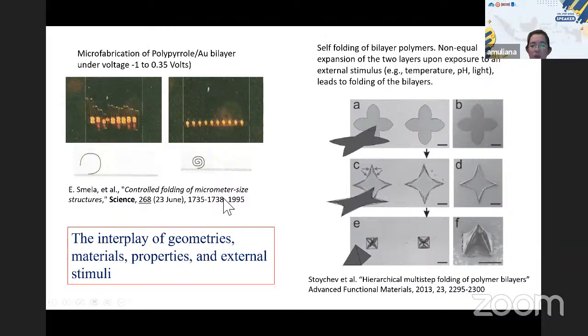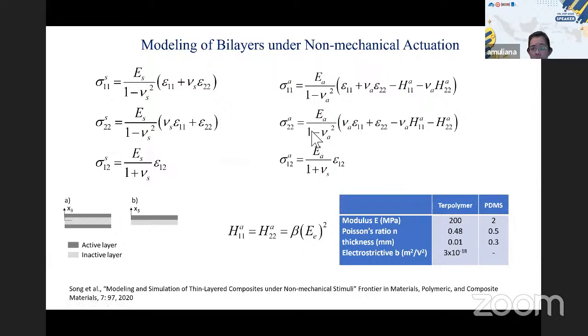So the purpose is for microfabrication. When you have a very, very small scale, it's really difficult for us to generate a complex shape or complex geometry, right? So through the idea of this folding, you can achieve various complex geometry, but of course we need to know the interplay for all of these aspects. Just to give you a simple example of this bilayer, we have the constitutive model for the substrate. This is an inactive layer. And we also have a model for the active layer. Now, depending on the activation mechanism, in this example, we show the electric field, right? So that's why we need the constitutive model for the electric field.